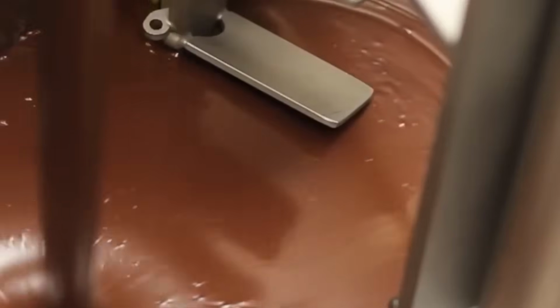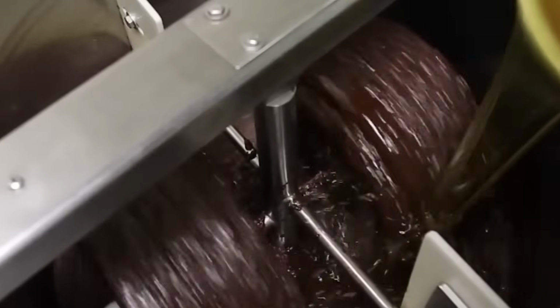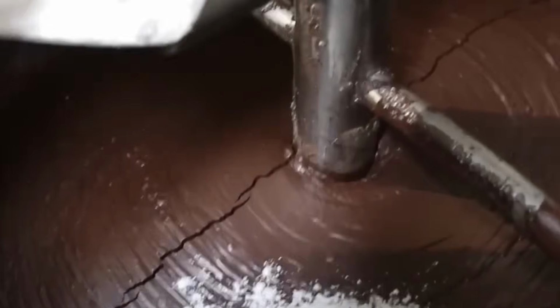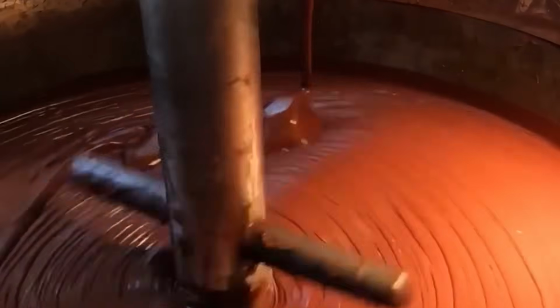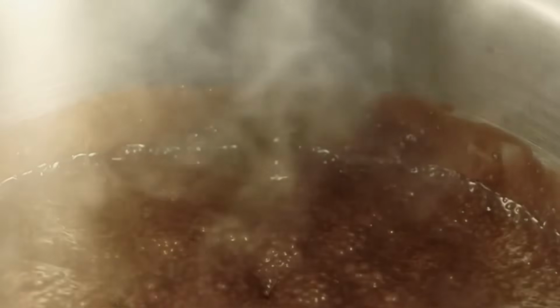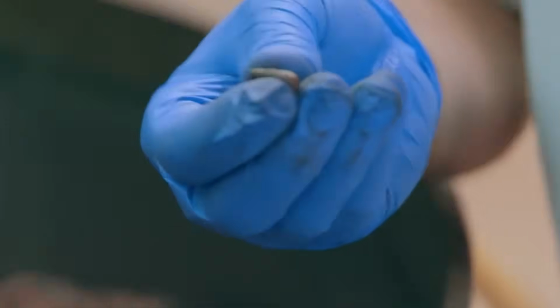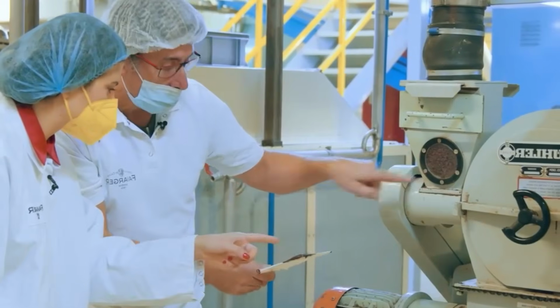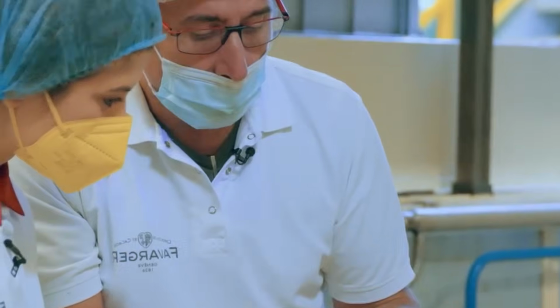After conching, the now liquid chocolate mass is pumped through a fine mesh filter to remove any remaining solids, and then enters the tempering system, which is a temperature-controlled series of heat exchangers and holding tanks that bring the chocolate through a controlled heating and cooling cycle designed to stabilize the cocoa butter crystals into the desired form V structure, which provides gloss, snap, and resistance to fat bloom. The tempering process requires careful monitoring of viscosity, temperature, shear rate, and time to produce a chocolate that will remain stable during storage and distribution.